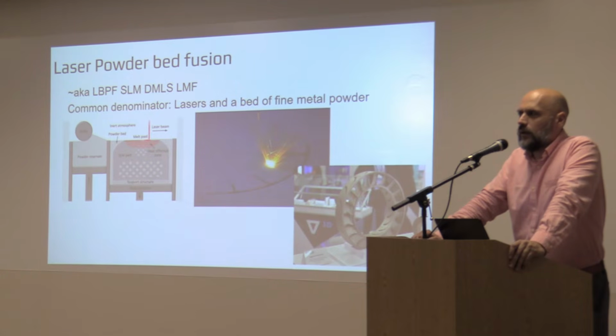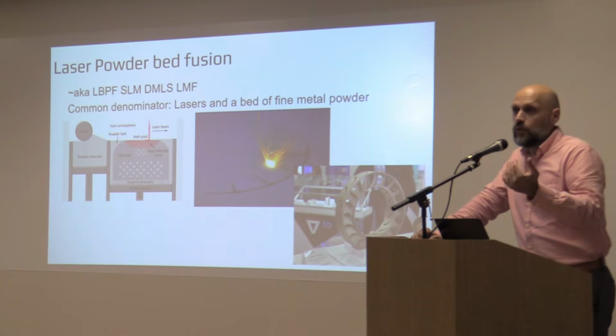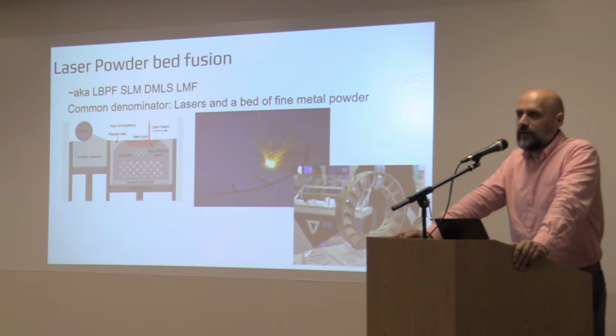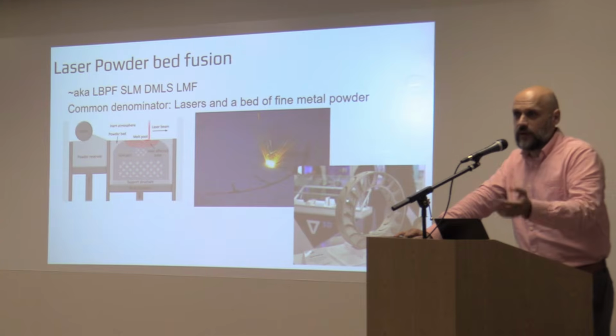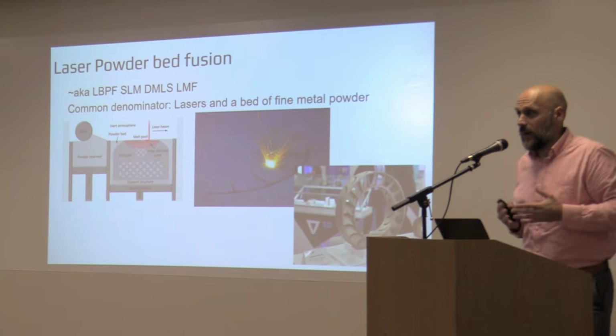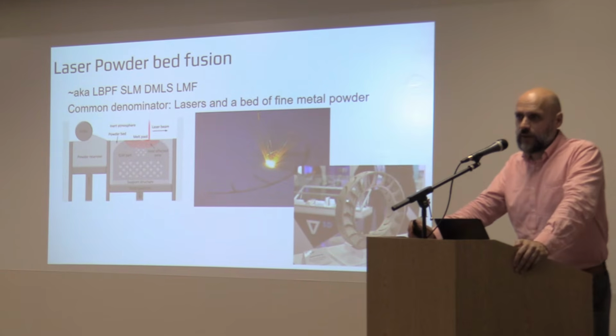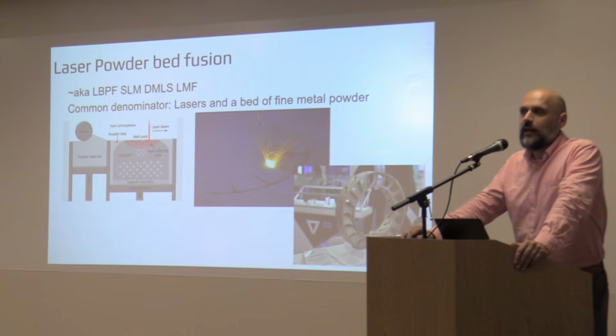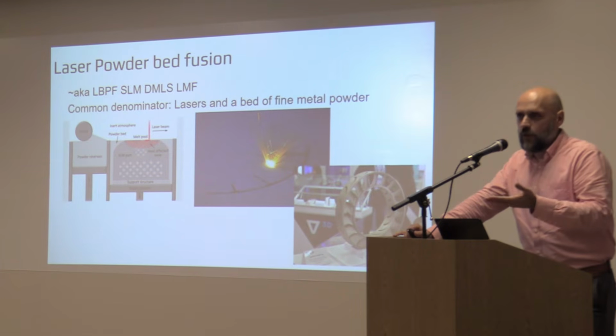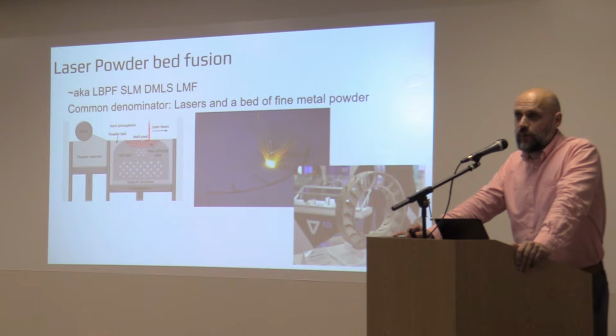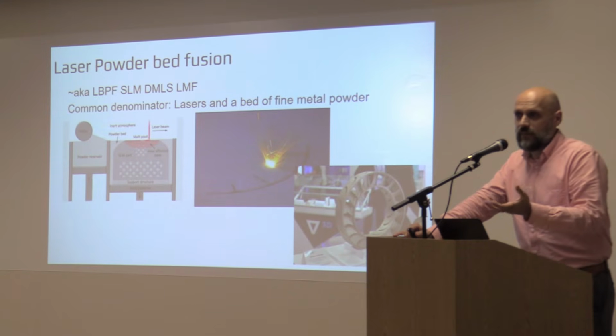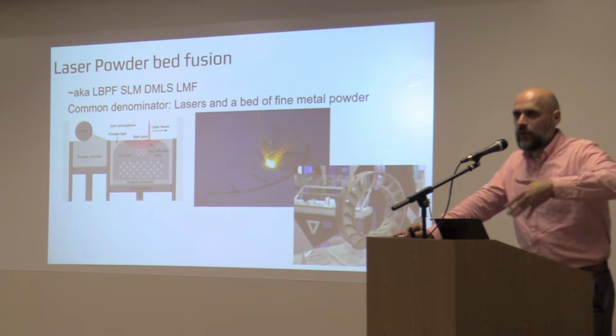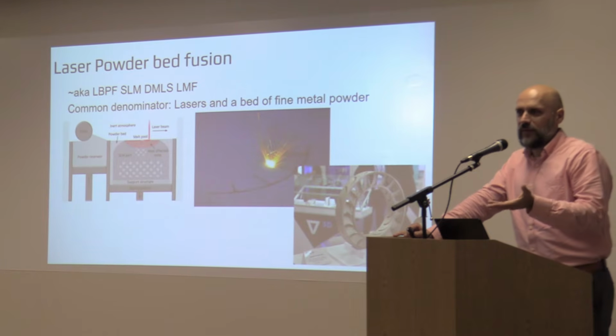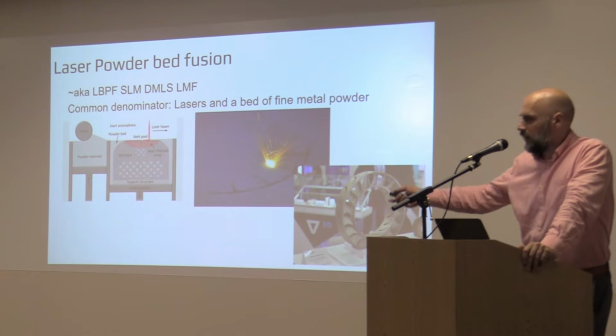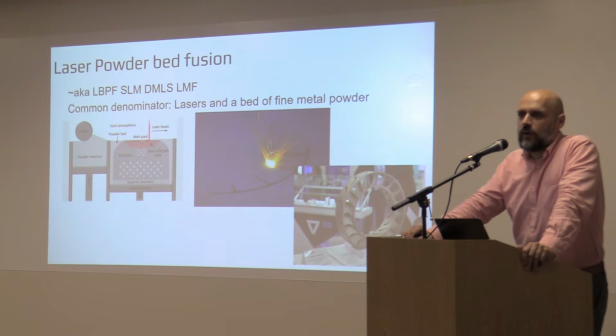And the most challenging thing, and I would say a holy grail here, is tool steels, right? Things that get very hard on quenching. When you quench steel, you make martensite, which means you undergo a transformation where you have dimensional change as well. So those stresses that you create with this tremendous cooling cause a lot of movement because of the residual stresses, and also cracking sometimes, right? Because you have to constrain it, you have to hold it in the base, otherwise it's going to move on you. But every time you do that, you load stress on the material, and eventually it just cracks and can rip the whole plate. It will rip the bolts here if you are not careful.